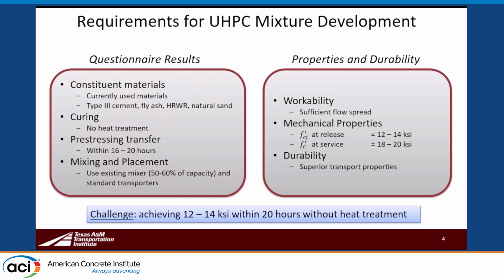Mechanical properties: we did a feasibility design study with typical TxDOT bridge girder sections, mainly the Texas shapes, which are I girders with a wider top flange and a fairly narrow web of about 9 inches. When we tried to push those girders to higher limits using UHPC, we found that a good release strength would be in the range of 12 to 14 ksi with a concrete strength at service of 18 to 20. And of course, we wanted to look at the durability and ensure that the expected good durability properties of UHPC, due to the very highly dense matrix, would be maintained in our mix.